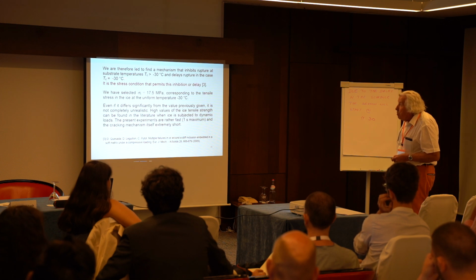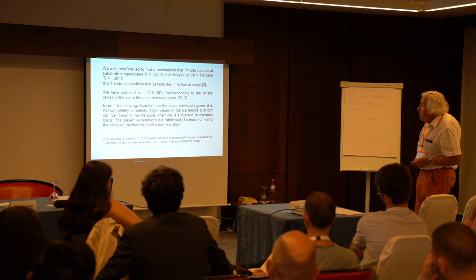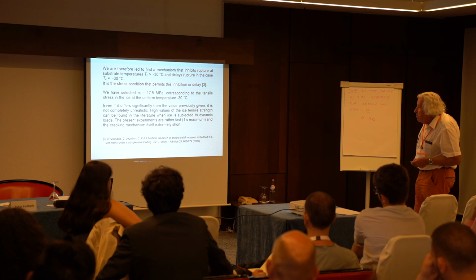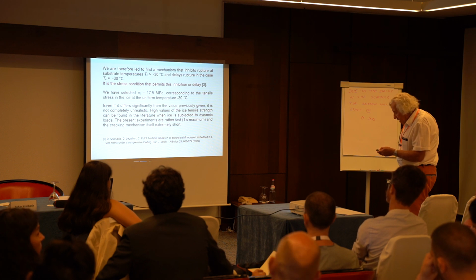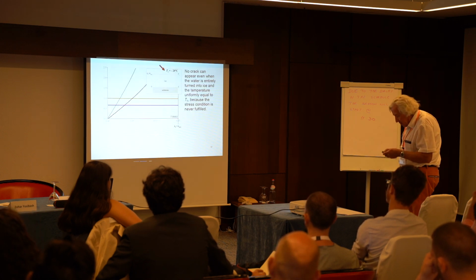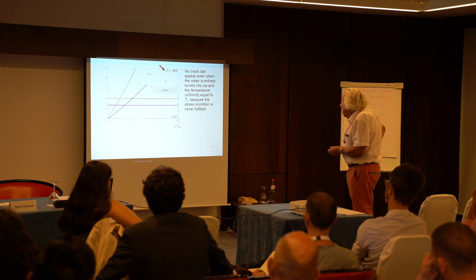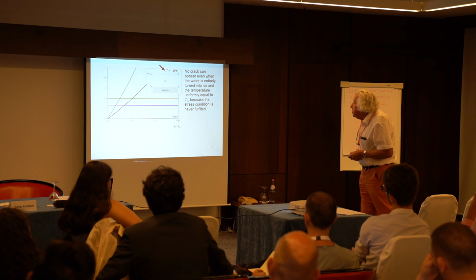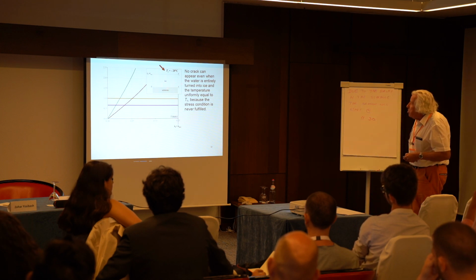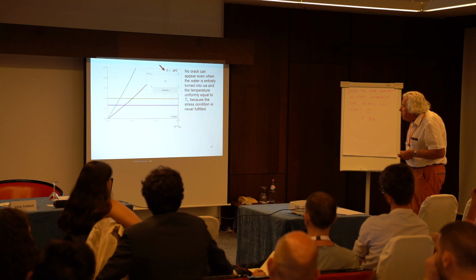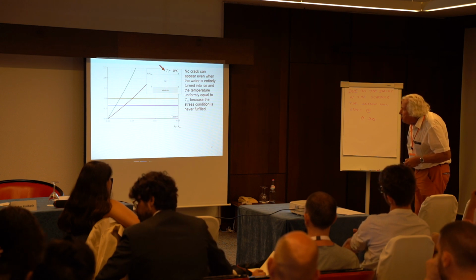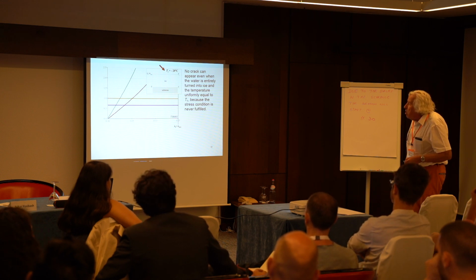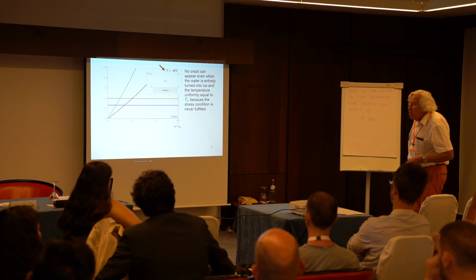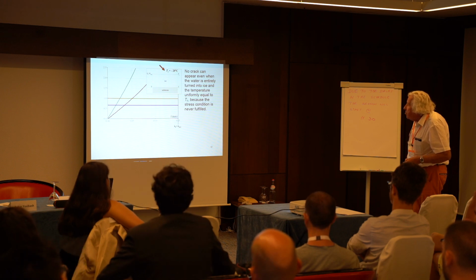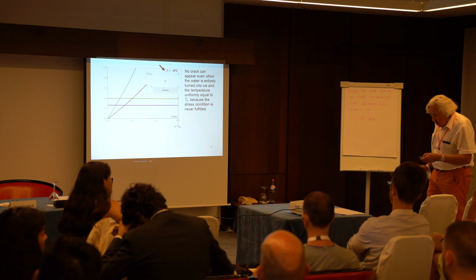It's just the thermal residual stresses that exist in the ice layer when the ice is at this temperature. Okay? So we have selected this value for sigma c. And then what happens? Now again we consider the temperature minus 10 degrees Celsius, we wait a long time, the temperature is homogeneous through the ice layer, the stress is homogeneous through the ice layer, but sigma is smaller than sigma c. So, okay, this is the energy condition, this is the stress condition. Here you see there is no match, okay?